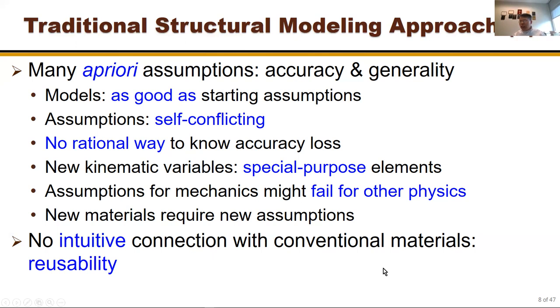There's no rational way to know the accuracy loss. You can make assumptions more sophisticated, but you don't know how much accuracy you've lost. In industry, people end up using the simplest model — for composite laminates, Classical Lamination Theory — because if accuracy isn't guaranteed, more sophisticated models have no use. High-order models also require new kinematic variables, meaning you have to create special-purpose elements not available in standard codes like Abaqus, ANSYS, or LS-DYNA.